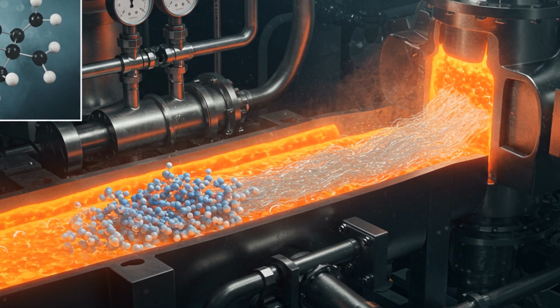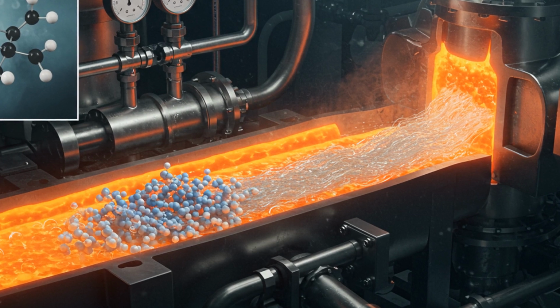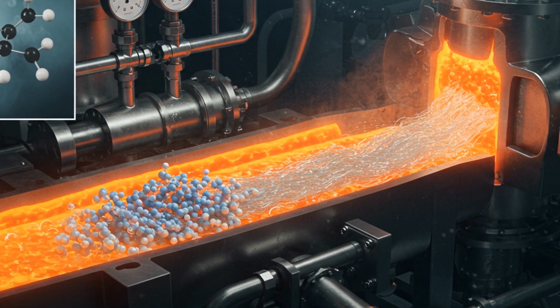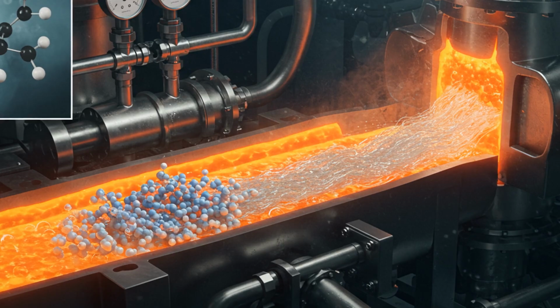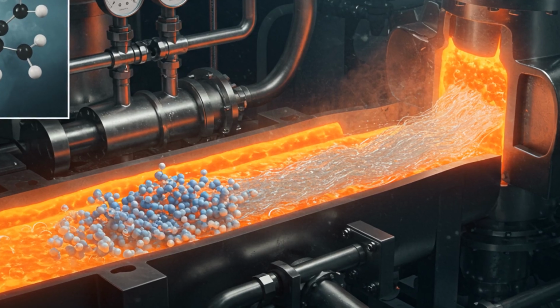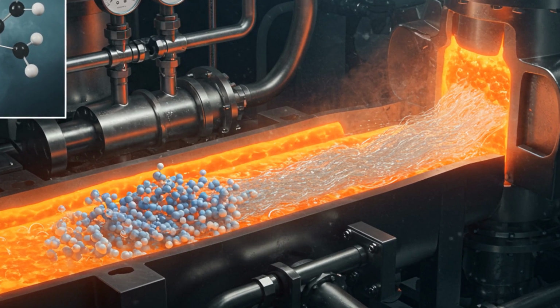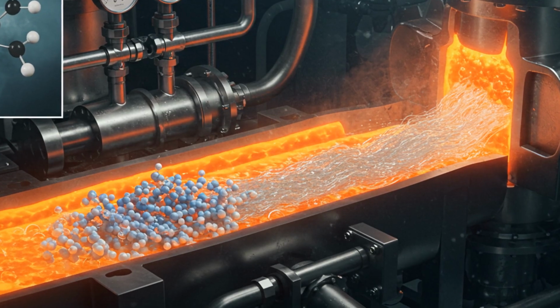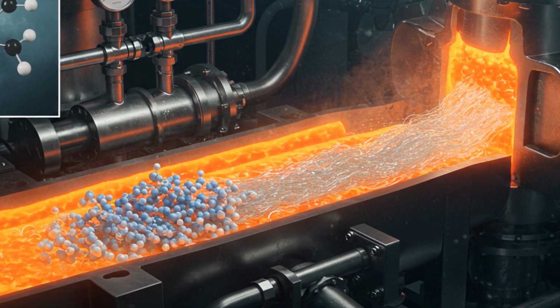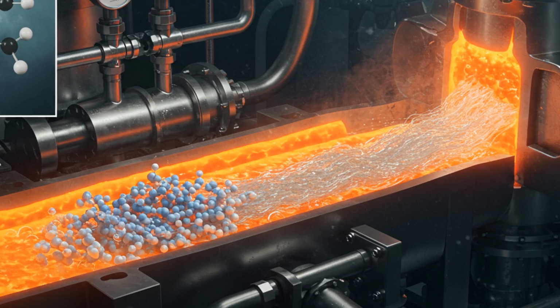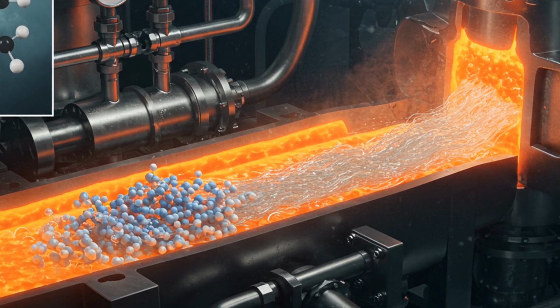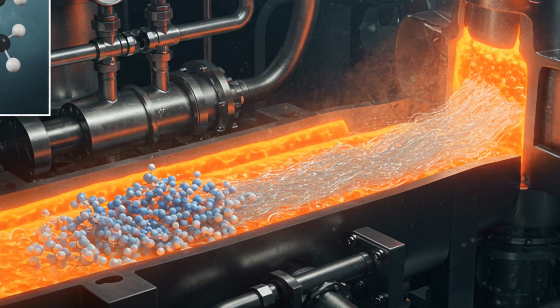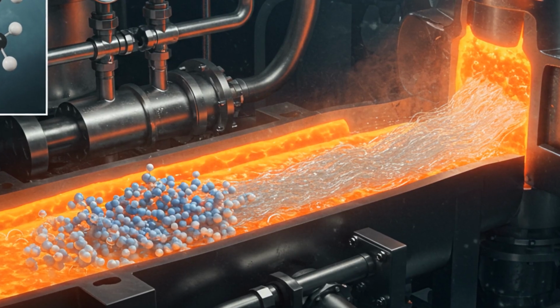For nylon 6, the route is different. Caprolactam undergoes ring-opening polymerization at temperatures near 240 to 260 degrees Celsius. In both cases, the goal is long chains, measured by intrinsic viscosity or melt flow index. The longer the chain, the higher the molecular weight, and the stronger the fiber, up to a point. Crystallinity forms as chains pack in lamellae. The degree of crystallinity controls stiffness and melting point.